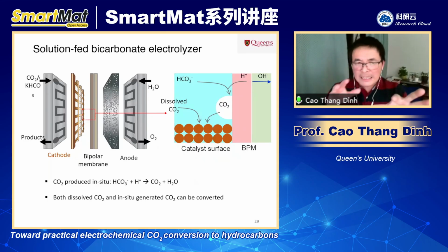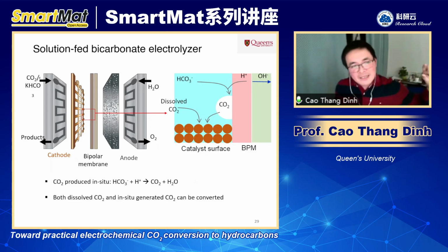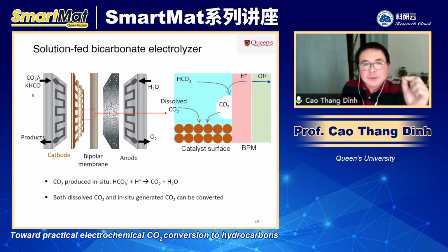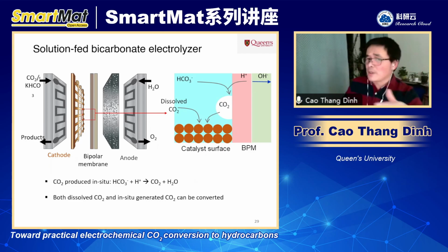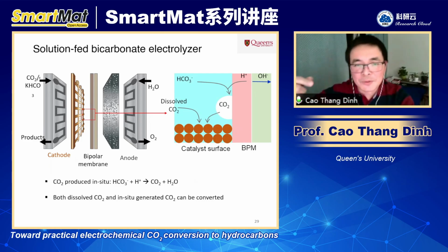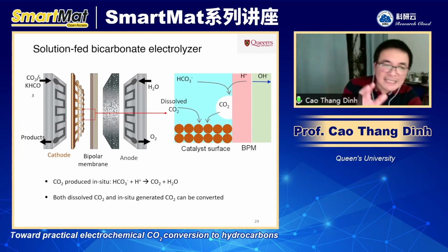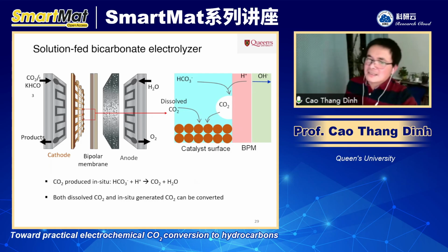So I look at the different systems for CO2 conversion in the aqueous phase, and I'm really interested in one cell configuration. It's called the bicarbonate electrolyzer. This cell configuration was invented by Professor Curtis Berlinguette at the University of British Columbia here in Canada as well. What happens in this system is that instead of feeding gas CO2 into the system, you use the bicarbonate in solution, with a very high solubility there. And when you feed it here, the bicarbonate can be converted to CO2. So the CO2 is now generated inside your system, inside your electrode. That CO2 is different from when you feed the CO2 directly into the solution.